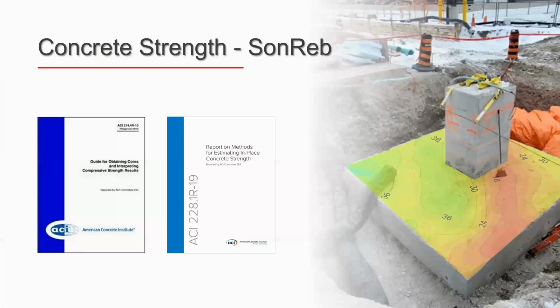If you remember, I talked about combining the results of rebound hammer with ultrasonic pulse velocity. We did a very interesting job in a couple of projects in the GTA area where clients were very hesitant about taking cores. So we came up with the SonReb method, an alternative NDT approach to assessing the strength of concrete. One of them was a footing element in a project site in the Toronto area, and the client was interested to verify the strength of concrete.